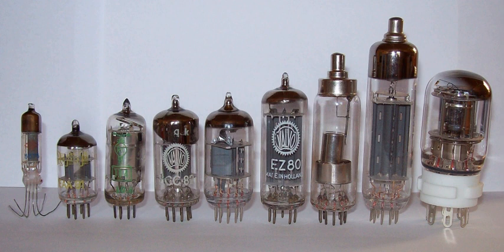The vapor is deposited on the inside of the glass envelope, leaving a silver-colored metallic patch which continues to absorb small amounts of gas that may leak into the tube during its working life. Great care is taken with the valve design to ensure this material is not deposited on any of the working electrodes. If a tube develops a serious leak in the envelope, this deposit turns a white color as it reacts with atmospheric oxygen. Large transmitting and specialized tubes often use more exotic getter materials, such as zirconium.